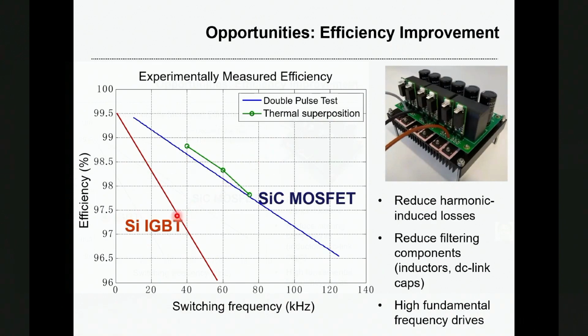As we all know, for silicon IGBT based hard switching converters, the switching frequency is normally below 20 kilohertz, with an efficiency around 98.5%. But with the fastest switching silicon carbide MOSFET, this switching frequency can be extended to 40 kilohertz or even higher. This high switching frequency capability can help to reduce harmonics-induced losses, reduce filtering components, including both the AC side inductors and the DC link caps, and also enable high fundamental frequency drives where you have high speed and a high number of poles for the electrical machines.